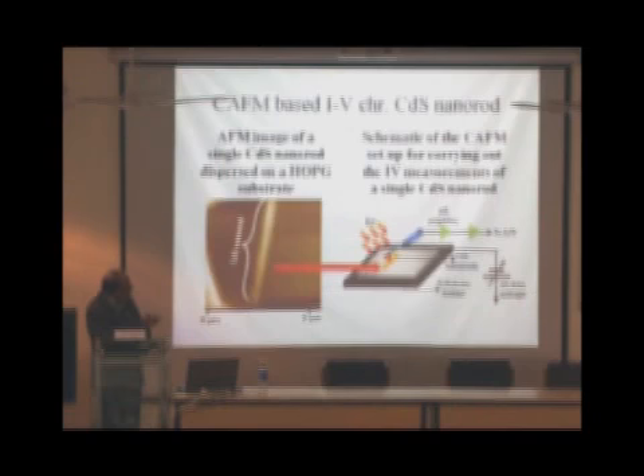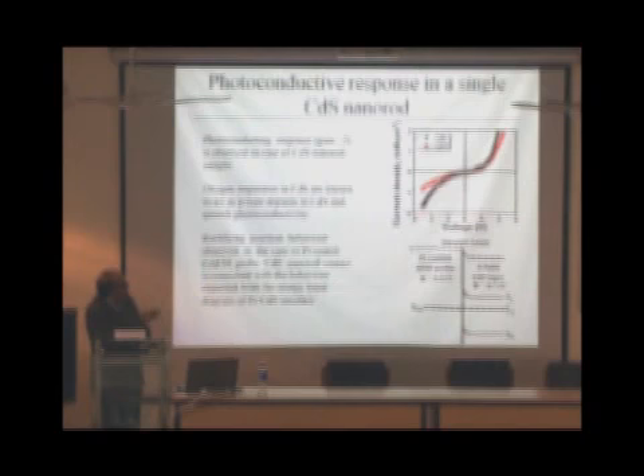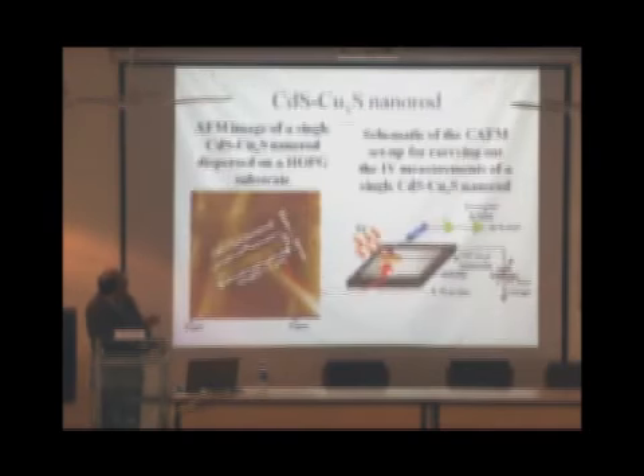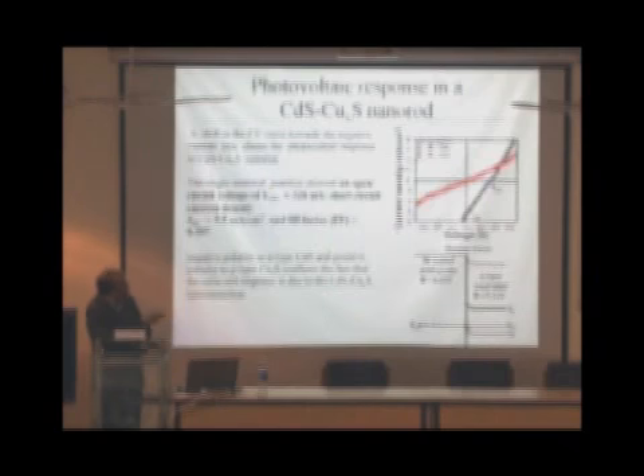This is a cadmium sulfide nanorod. This is the AFM picture of this. And what we see is this is the IV characteristic. If we put light, we see some photoconductivity, because cadmium sulfide is a photoconducting material. And this is another experiment which we did after forming the junction. And what we see is this is the dark IV characteristic and this is the light IV characteristic.